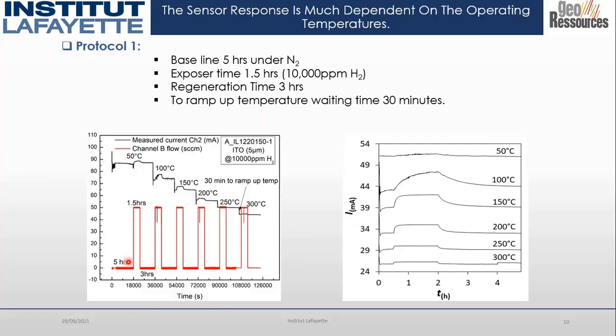So this is our first test. This is the scale of the current, and this is the scale of the time. At the very beginning of the protocol, we kept our sensor under nitrogen for 5 hours for a suitable baseline. Then we exposed it to 10,000 ppm of hydrogen for 1.5 hours and gave 3 hours to regenerate the sensor. After each regeneration, we changed the operating temperature, like from 50 to 100 degrees. When we switch from 50 to 100 degrees, we wait 30 minutes to stabilize our sensor. And in this way, we vary the temperature from 50 to 300.